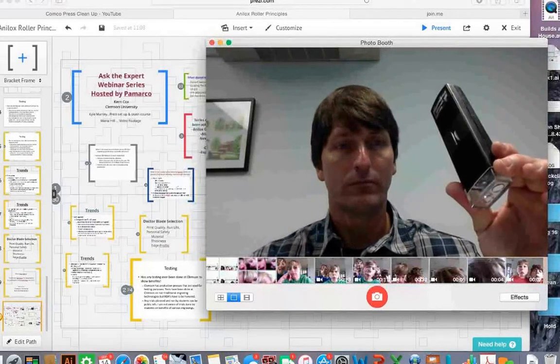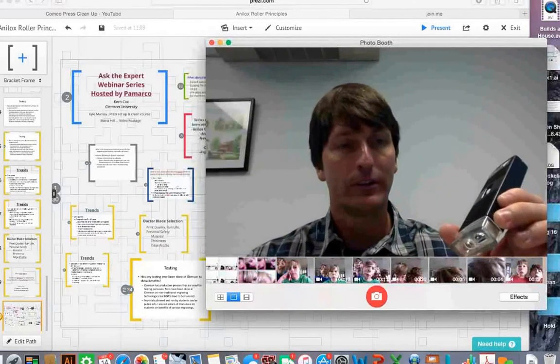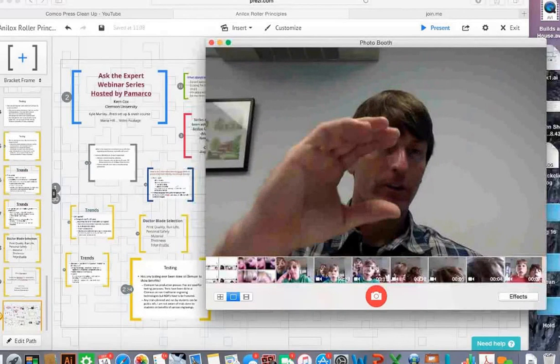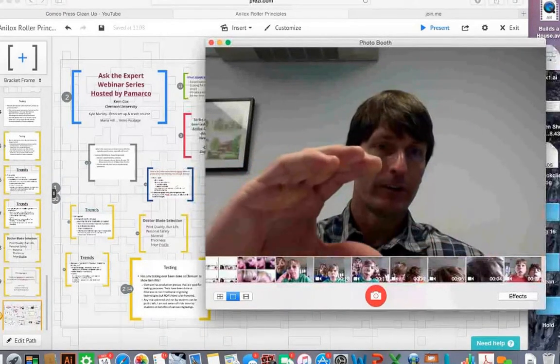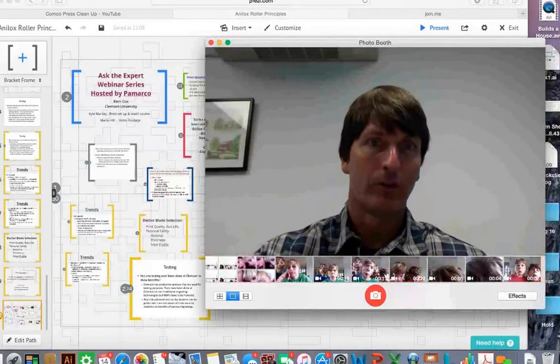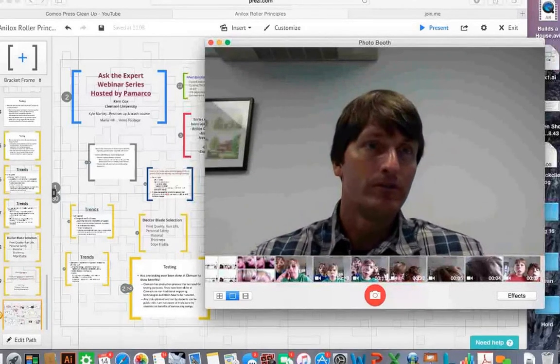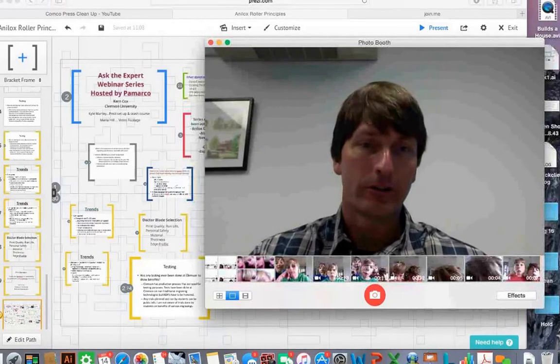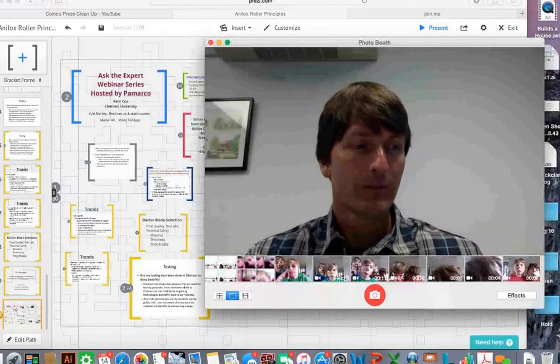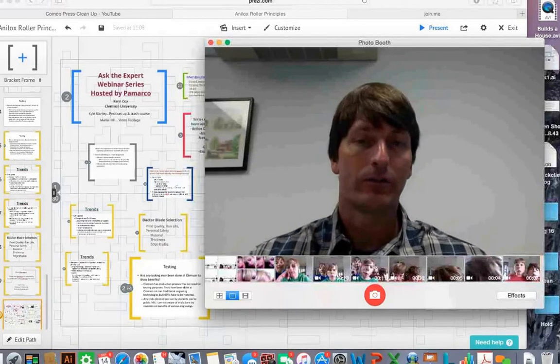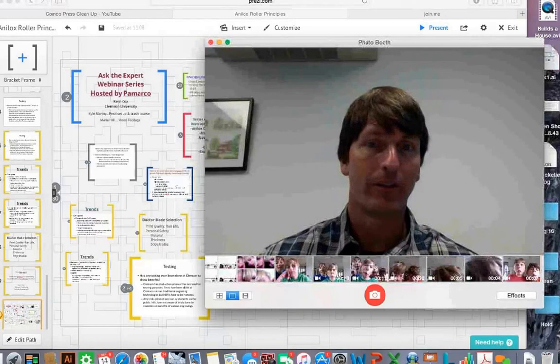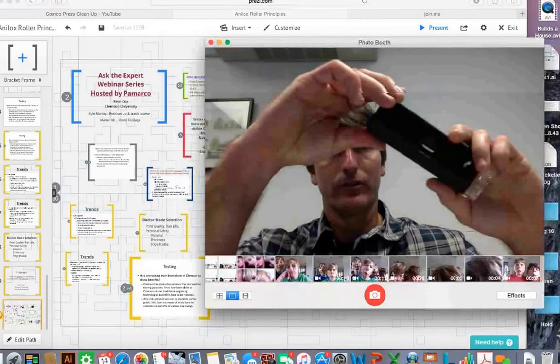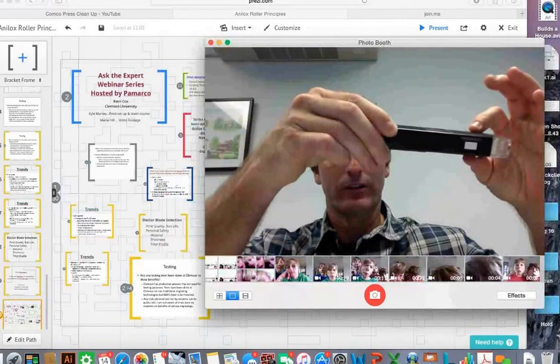For field testing, I like a microscope with a light, or small digital microscopes available from Amazon with a screen that can zoom and send pictures to your computer. For 800 cells per inch or lower, a 30X or 50X microscope works well. Above 900 cells per inch, you might need 60X, 70X, or 100X to really look down in those cells. The challenge with higher magnification is that any wiggle on the device changes your focus.